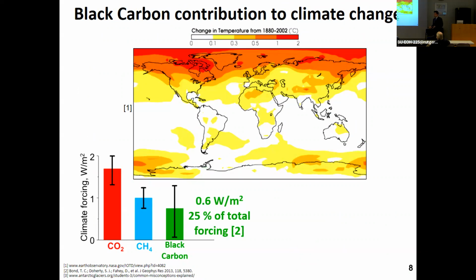And the previous IPCC report, a report by the Intergovernmental Panel on Climate Change, had listed black carbon together with CO2 and methane as the three largest contributors to global warming based on their radiative forcing. But as you can see over here, the black carbon estimation had the largest uncertainty. And this was again because of the very complex structure that I showed you earlier, this porous structure that these nanoparticles have, and of course is way more complex than a simple molecule like CO2 or methane.